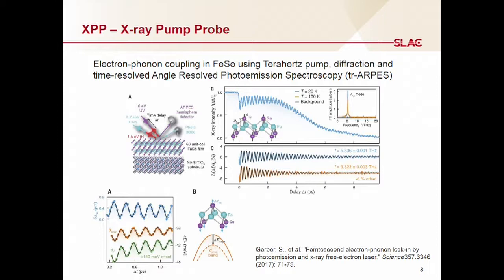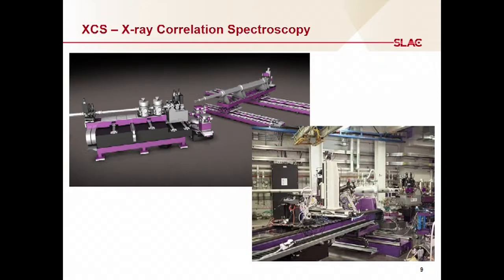And what they found is that there's very much a correlation between the lattice vibration, the phonon mode, and the electron energy states. This shows evidence that there is this electron-phonon coupling, which enhances the energy states, which can lead to these exotic effects. So that's one example of a very intense pump-probe experiment.